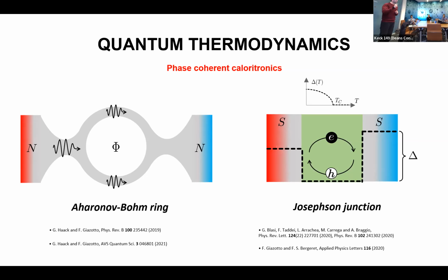You're perfectly right. The thermoelectricity comes from the particle-hole asymmetry. Particle-hole asymmetry in the transport domain means that your transmission function is asymmetric with respect to the energy. And you can make this transmission function asymmetric, in the case of the Aharonov-Bohm ring, by using this magnetic flux. And indeed, you can see that it becomes asymmetric and you have a Seebeck coefficient, for example. In the case of Josephson junctions, this is possible by playing instead with the Josephson bias, so the superconducting phase difference between the two superconductors.